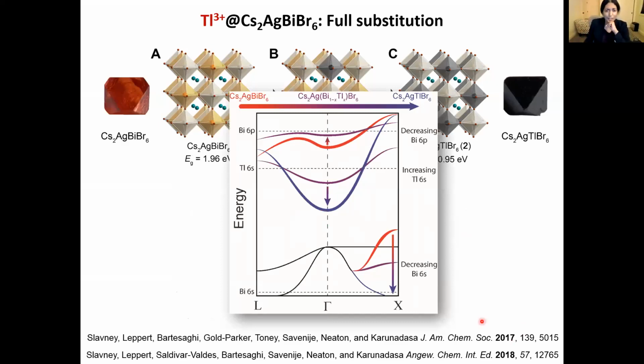It's a little busy, but if you will look at this red line here, this is my silver bismuth double perovskite. And as I start removing bismuth, I'm removing the maximum of the valence band at X, because I'm removing the s orbitals. And as my valence band maximum goes down, down, down, the maximum is left at gamma. I'm not just removing bismuth, I'm also adding thallium. Thallium brings empty 6s orbitals, and that gives me a conduction band minimum that keeps going down, down, down as I add more and more thallium. And so I go from this large indirect band gap to the small direct band gap. So it's very satisfying to understand both alloying, so stoichiometric substitution, as well as full substitution.